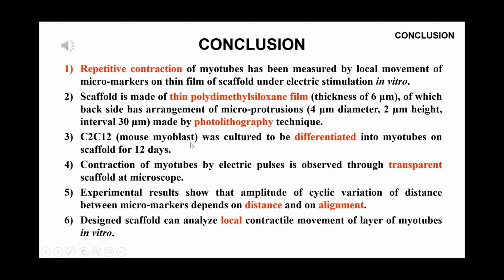3. C2C12 mouse myoblast was cultured to be differentiated into myotubes on scaffold for 12 days. 4. Contraction of myotubes by electric pulses is observed through transparent scaffold at microscope. 5. Experimental results show that amplitude of cyclic variation of distance between micromarkers depends on distance and on alignment. 6. The designed scaffold can analyze local contractile movement of layer of myotubes in vitro.